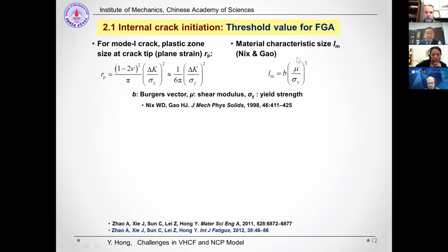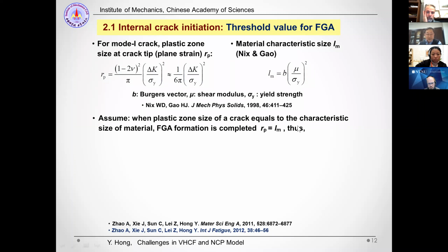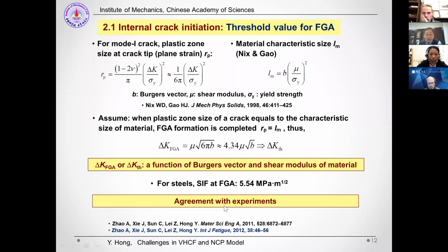We use the formula for plastic size at the crack tip as this, and also we use a formula to correlate microstructure characteristic size in relation to material parameters of shear modulus and yield stress. And we assume that when the plastic zone size of the crack equals the characteristic size of the material, the FGA formation is completed. Thus, we can obtain this result to show the delta K FGA.